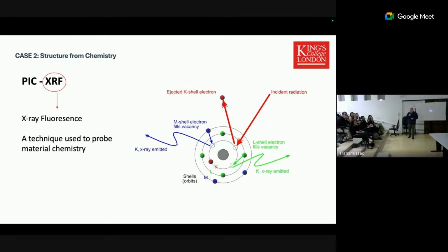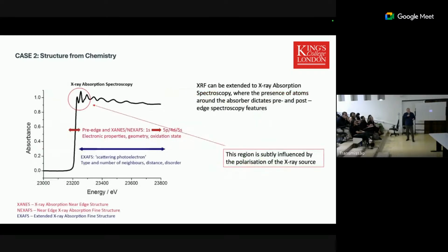So the technique is a chemical technique, it's not an imaging technique. We fire X-rays of a specific energy, and if they're absorbed by an atom, we can knock out one of the orbital shells. So one of the electrons will be knocked out, and then another will jump into its orbital shell and release a photon, which we can measure. So from this technique, we can normally just say, oh, this is calcium, or this is phosphorus. But by doing something a little bit more with it, we can actually start to say, well, this is calcium bound to oxygen, or this is calcium with its nearest neighbor being hydrogen or something like that.